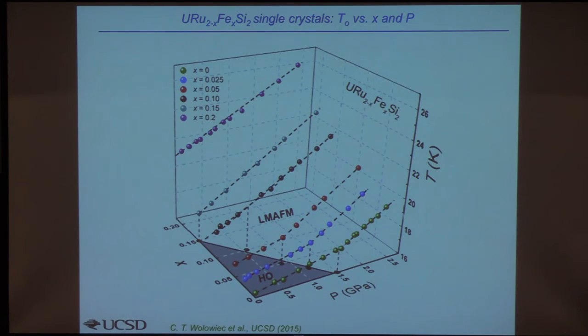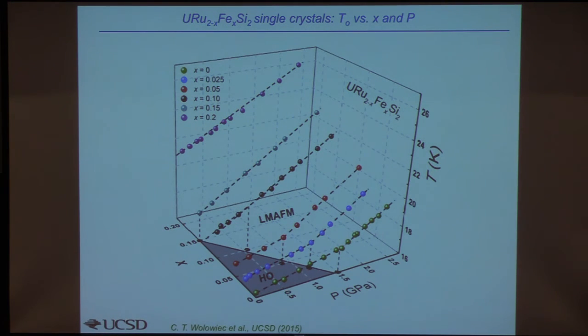Okay, this is basically the temperature at which the hidden order phase occurs in this region right here. And then this is the large moment antiferromagnetism, and there's a kink in this phase boundary when you go from one to the other. So as we add more iron, we're presumably increasing the chemical pressure, and so this should occur at a lower applied pressure, which it does, and then eventually at zero pressure when it's purely in the antiferromagnetic phase. Okay? So this shows you that they're at least equivalent, as I've indicated here.